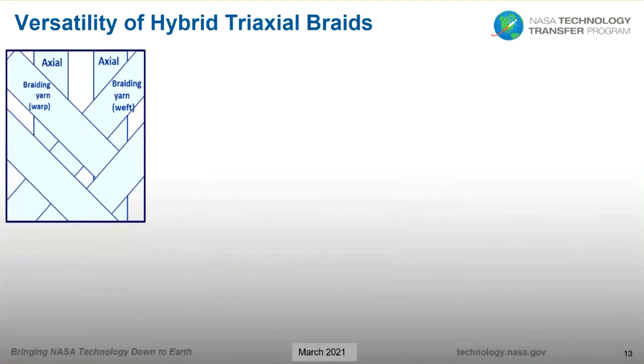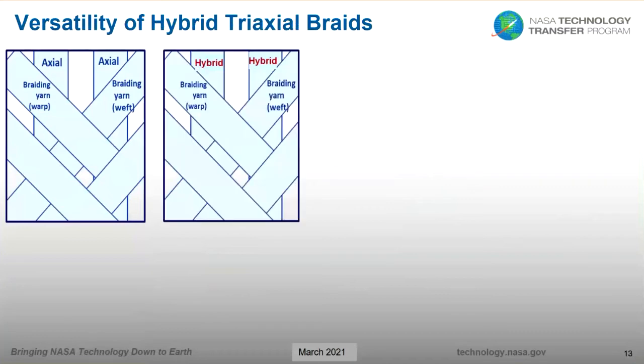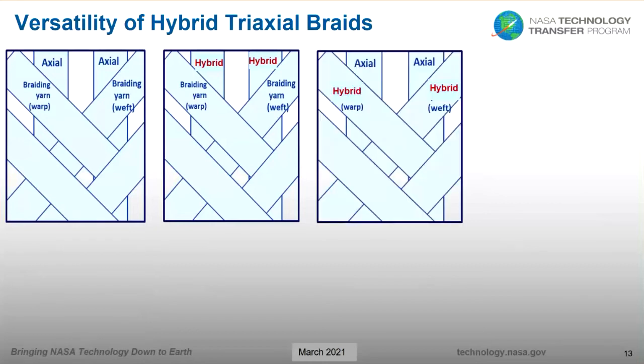So a benefit to hybridizing a braid is its versatility. A normal braid consists of axial yarns located in the 0-degree direction and bias yarns existing in the warp and weft direction. If you have an application where you anticipate failure initiating in the axial tows, then you can introduce the hybrid tow in only the axial tows while leaving your regular carbon fiber tows unaltered in the bias direction. If you anticipate failure initiating with only the biased tows, similar to what we noticed in the field strain image in the previous slide, then you can hybridize only the bias direction while maintaining the stiffness of the axial tows that are made of predominantly carbon fiber.